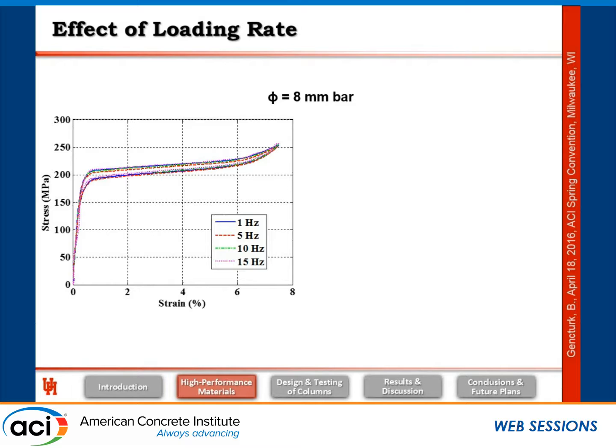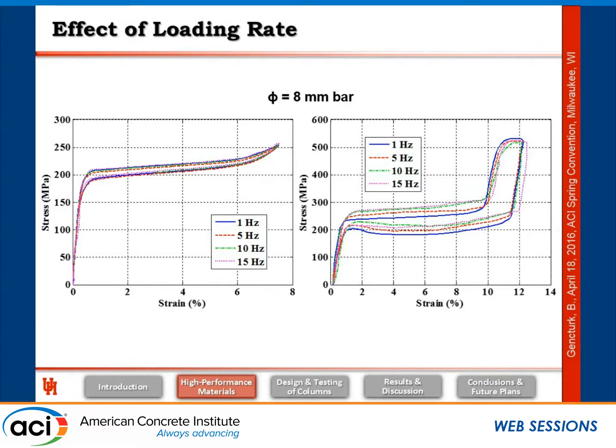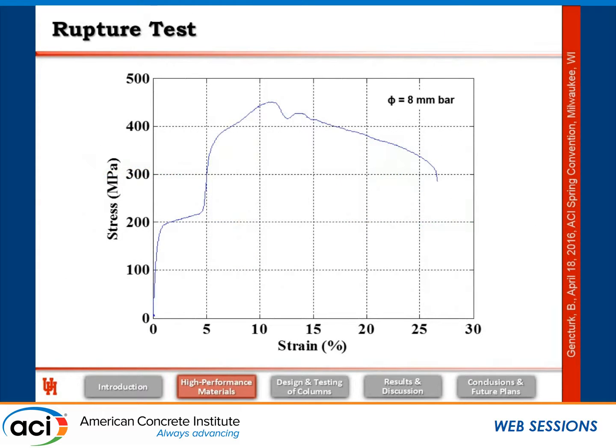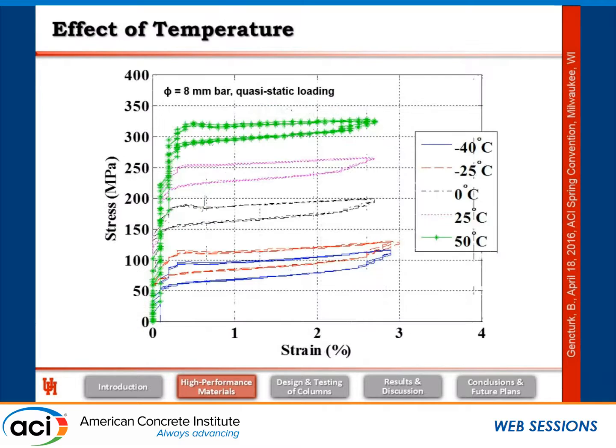Then, once the material survived the 7% strain cycles, we increased the strains up to, in this case, 12%. There was some shifting of the hysteresis loops, so if you increase the frequency, basically everything moves up. But again, very stable hysteresis loops. We didn't see any fracture in these tests. One of the bars, actually I think the same bar, we pulled to failure. As you can see here, there was an extensometer on the bar, and we measured the strains through the extensometer, not based on the actuator displacements. What we have seen is this material can really go up to 25% strain, which is very similar to a mild steel.